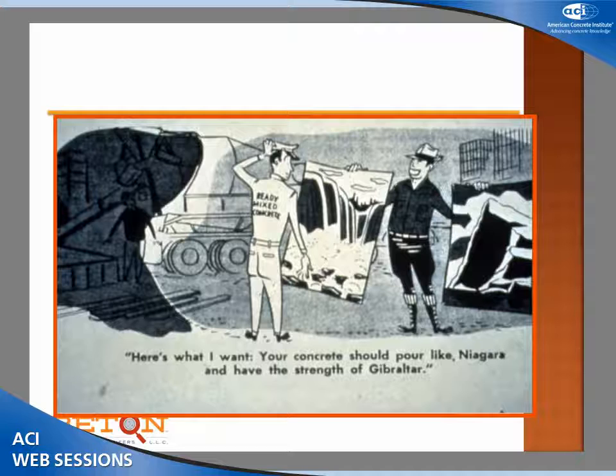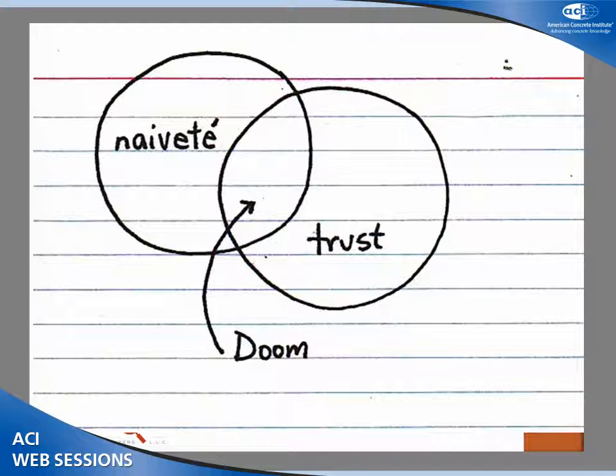Now, it doesn't matter. Slump's very useful if you're making concrete, because if you think you're doing the same thing and you take a slump and then you run another batch, right? That's how concrete's made, like cookies in small batches by elves and trees. If you check that second batch and the slump is different, you didn't do the same thing. You might be aware you didn't do the same thing, or you might be finding out you didn't do the same thing. So very useful quality control tool, absolutely useless quality assurance testing.